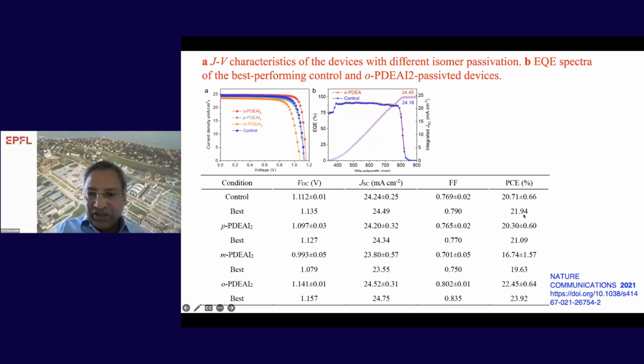The best efficiency is 22%. Now, if you substitute with the para on top of three-dimensional perovskite, the efficiency is lower than the control. If you take the meta-substituted one, the efficiency is even significantly lower, 16%. Oh, the best one is 19%. However, the ortho-substituted one gives you 24% efficiency.